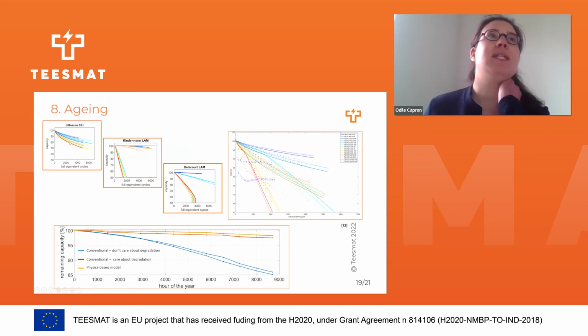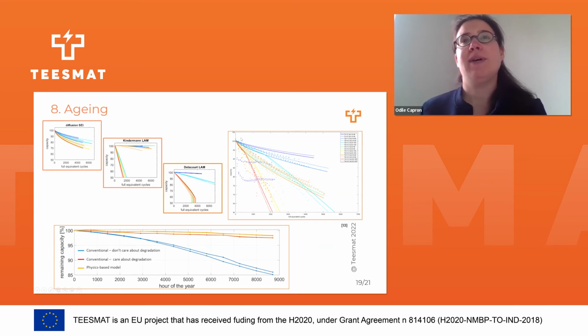So it was only a single particle model. And we take the loss of active material and SEI, for the solid electrolyte interface. So in fact, when we try to implement this mechanism and corroborate with the experimental results, we can see that the full plain lines are the simulated results, whereas the dots are the experimental data. So the amount of experimental points for the capacity as a function of the cycles.